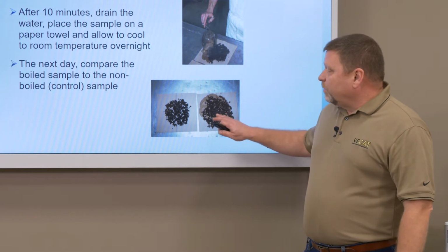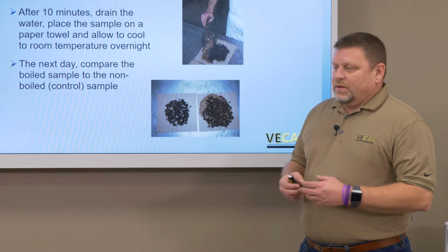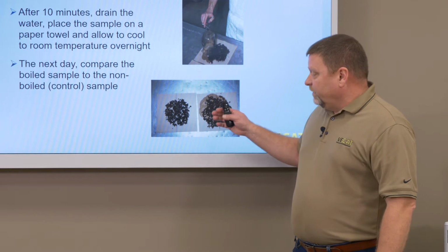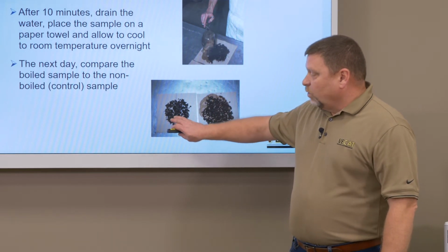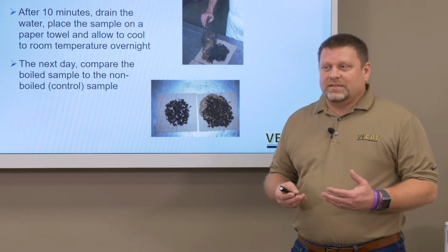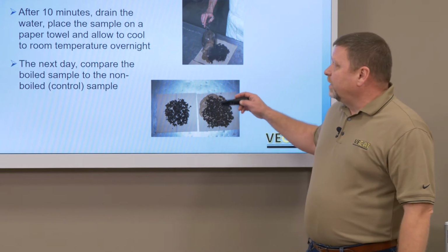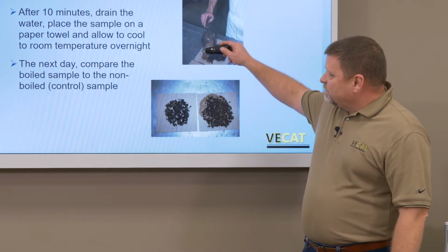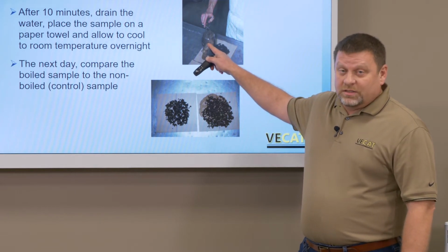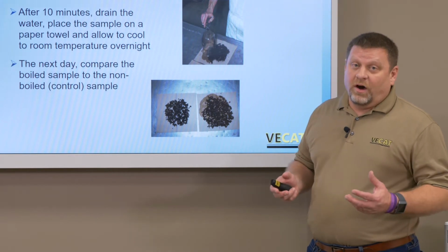So just allow your sample to cool, and then basically you're comparing how much binder would have boiled off the aggregate visually compared to your reference sample. It's a visual comparison, and that's where people say it's an opinionated test. Well, I can understand the opinionated comment, but when I see asphalt binder in this beaker, like this much binder, that's telling me that beaker was clear when they started the test. Now it's very dark. That's telling me that the binder is coming off.